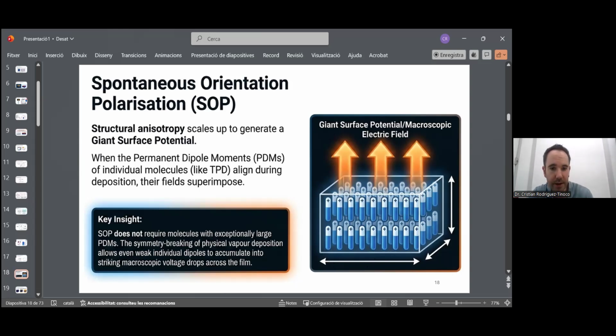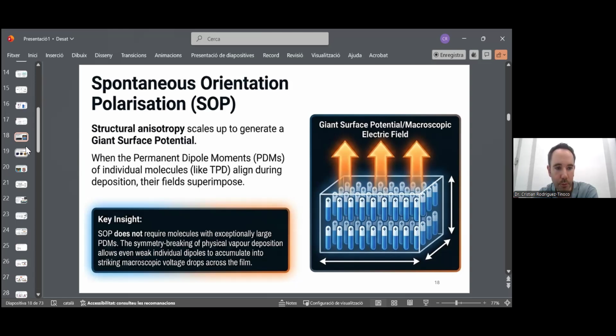So at the end, if you grow a layer of 100 nanometers, for example, which is a typical size of layers of films in electronic applications, you can end up with a thin film that spontaneously generates a voltage difference of many volts, okay, from one side to the other of the film. And this can have many applications, okay? You can also play with the polarization, okay? When you change from the glassy state to the liquid state, and if in the glassy state you have this kind of giant surface potential, when you convert the system into a liquid, you generate a current pulse because of this depolarization, okay? And this can be used, for example, in neuromorphic applications, okay, which is something that we are now starting to explore in our group.